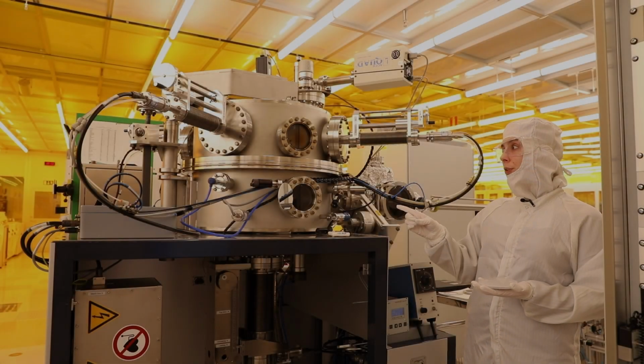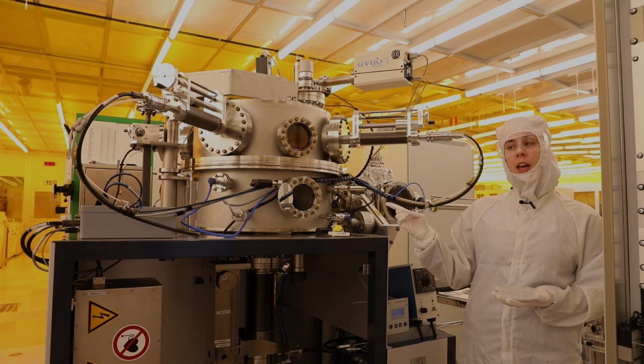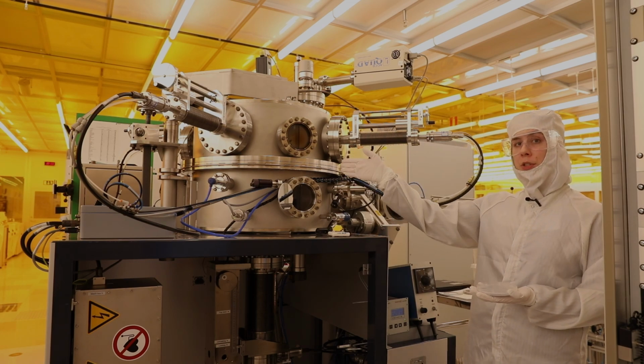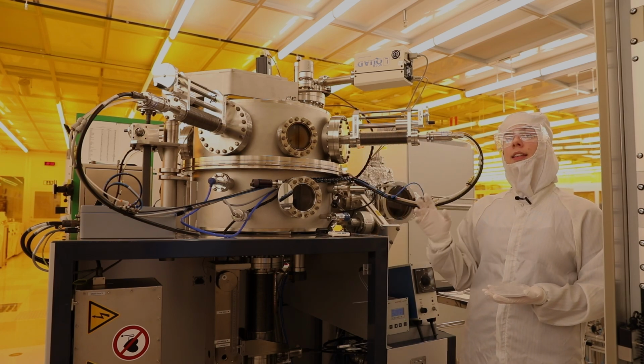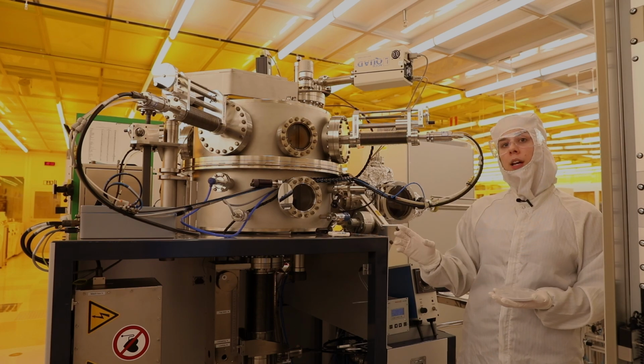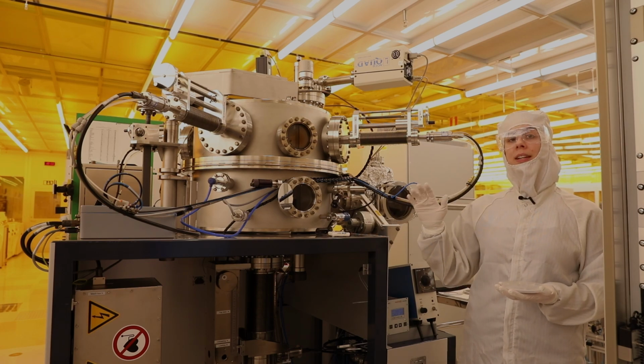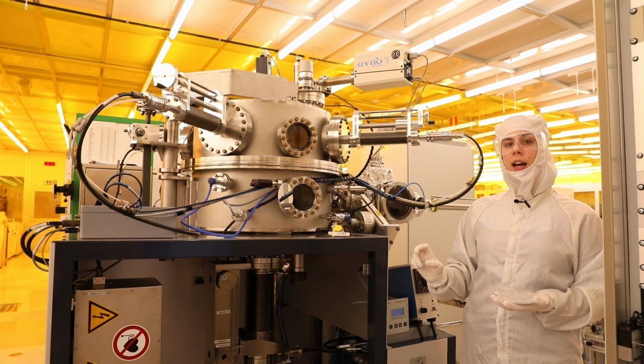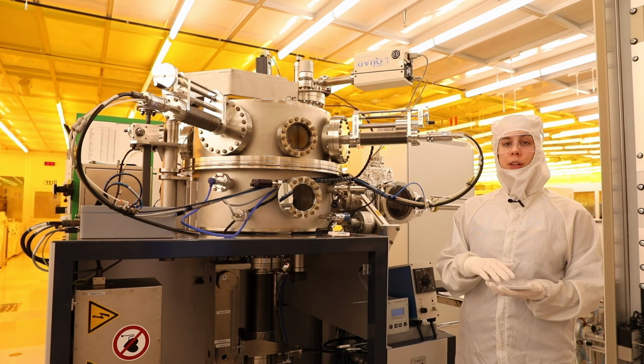metallic film. So now we are at the sputtering tool where we're going to deposit the film. And this is the deposition chamber where we're going to do it, which is currently sitting at a very good vacuum where the pressure is somewhere below 10 to the minus 8 millibar. And the reason for that is we want to avoid contamination of our films during deposition.